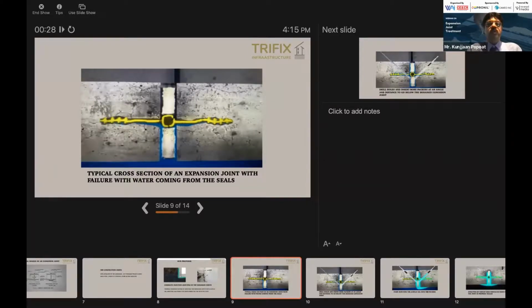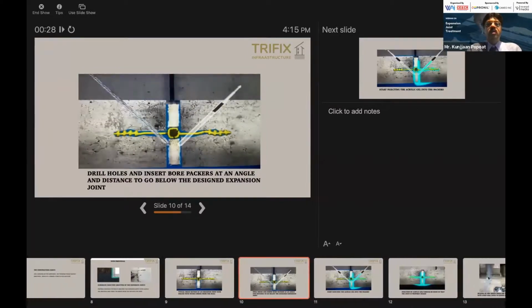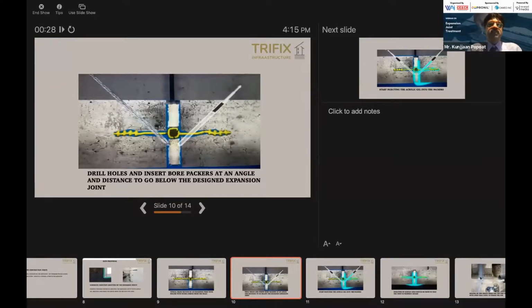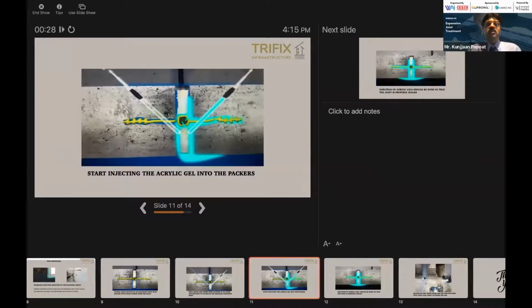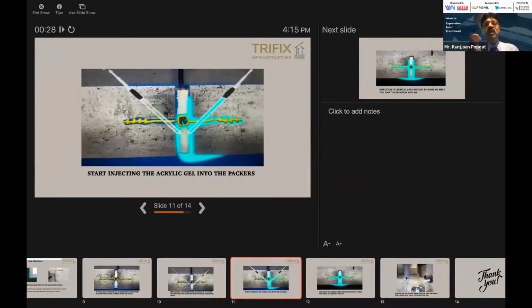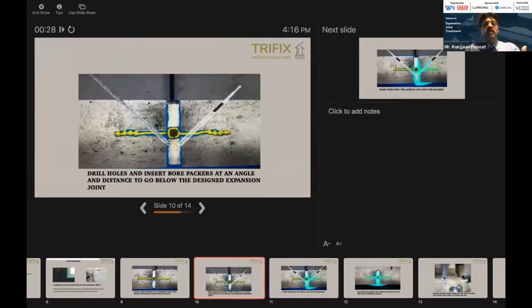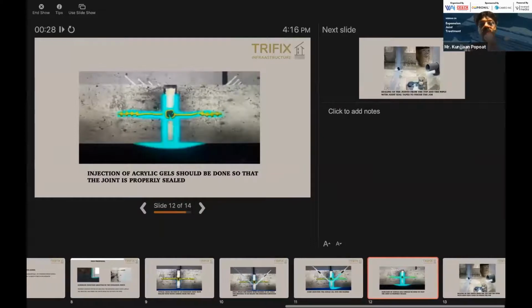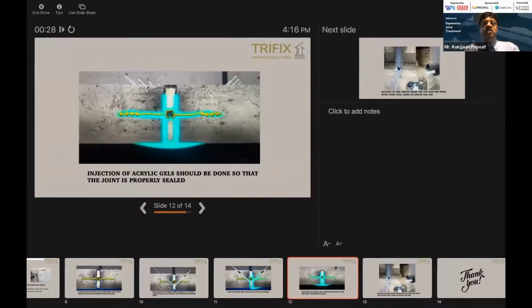So what we proposed was to drill the hole and insert the packers beyond the seal, and it was designed at such an angle that the packers would go beyond the seal. Then we slowly started injecting acrylic gel into the packers, and in such a way we went on doing it so that it forms a seal below the expansion joint.